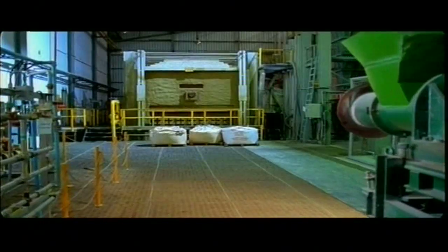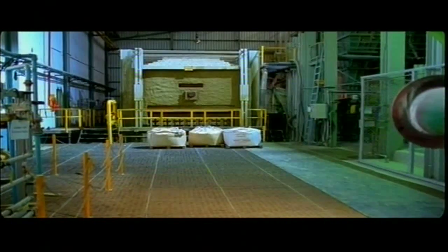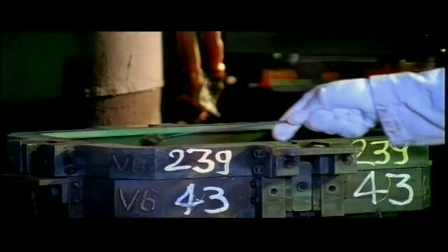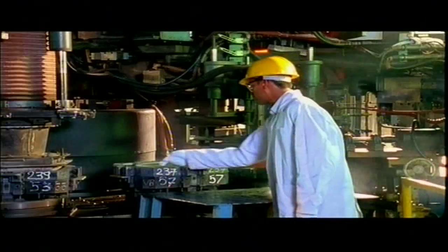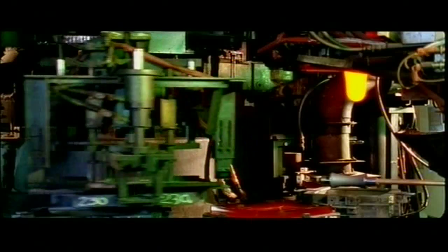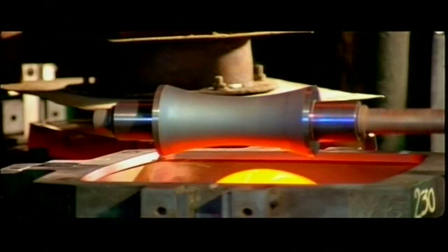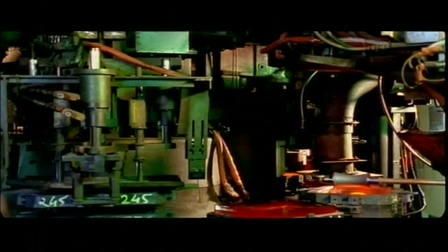The company has 3 furnaces for melting the quartz sand for funnel and panel glass separately on independent lines. Capable of melting approximately 100 metric tons per day, these cross-pot regenerative furnaces are fired by natural gas. The molten glass, with a temperature of around 1010 degrees centigrade, then flows from the melter to the forming press to be pressed under very high pressure into the desired shape and contour.